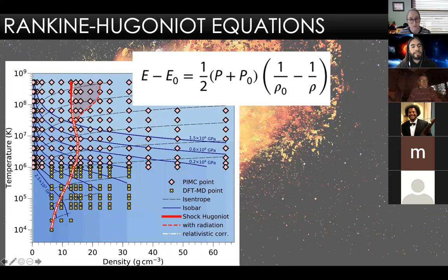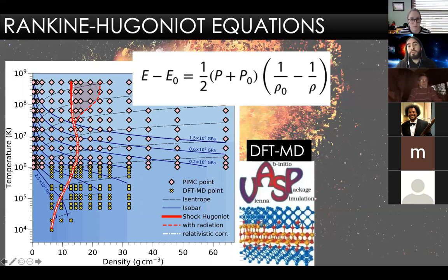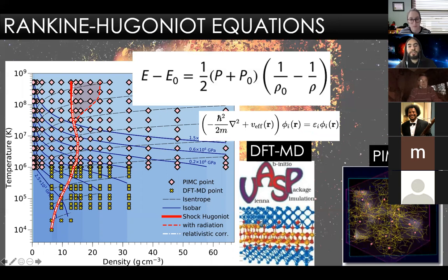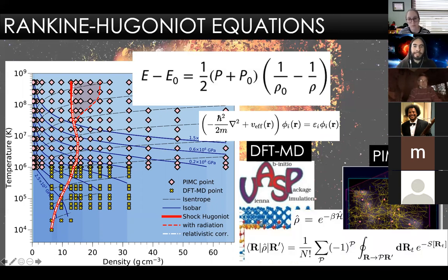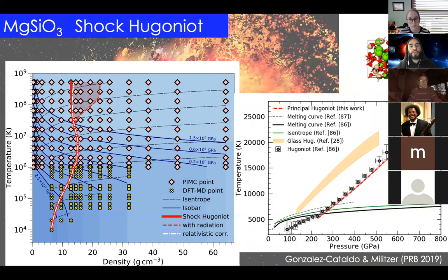So the way we do it is we basically take a material, we simulate it at different temperatures and densities, and we try to solve this equation to find which states satisfy these equations. And if we find these states, we're basically finding one point in the Hugoniot curve. To do so, we use density functional theory molecular dynamics, which is a technique in quantum mechanics, and also path integral Monte Carlo. In DFT, we have Schrodinger-like equations where electrons are waves, wave functions. And in path integral, the electrons are literally paths that you have to integrate over all possible paths. And that gives us a description of the material itself. So when we obtain this Hugoniot curve and we compare it to experiments, we have observed already that we have a beautiful agreement between the experiments, which are these points with error bars, and the curve that we predict from our simulations.